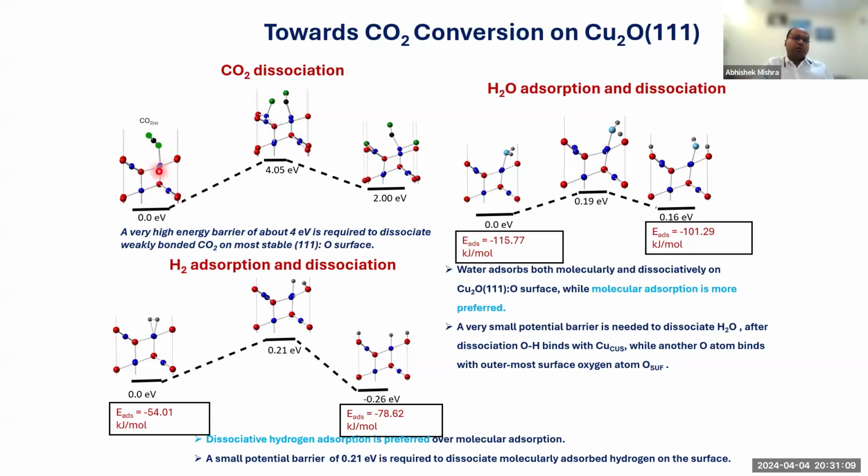having a bond here on the upper side of the copper oxide. We tried to dissociate it and did the calculation, attaching the oxygen on the various sites available here. And this was the most feasible one, the one at the corner of our unit cell. If you look at this value, it is suggesting that this is not going to happen. The activation barrier came out to be really very high. And as a result, we did not proceed in this direction to further convert into carbon monoxide or something. And then the only option left was to identify the source of hydrogen.